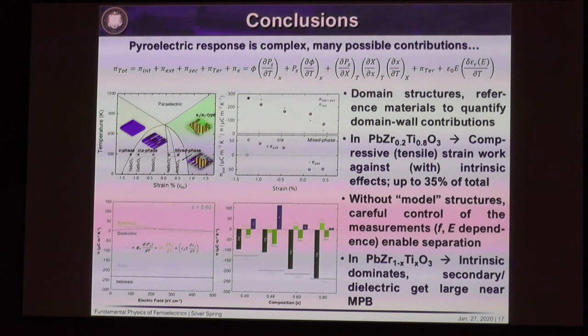So we've actually done measurements in both ways. Many of the things that I've shown you for these loops are almost quasi-static. They're very slow types of measurements. So you should think of that as almost being at remanence in these systems. We have tried to do faster measurements. It cuts down on the accuracy of our pyroelectric and electrocaloric measurements to do these things faster, but it's a balance. So if you wanted to do that, I think we can think about ways of doing those experiments both on field and at remanence. At remanence is relatively easy. On field's a little harder. It's a good question, though.